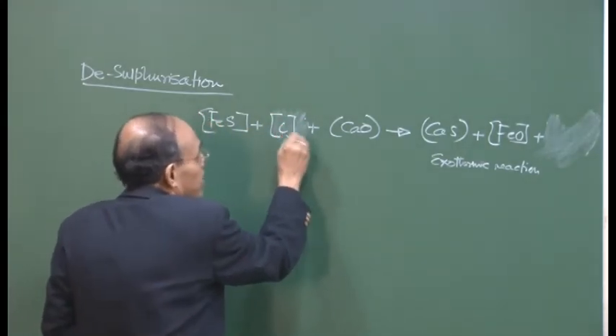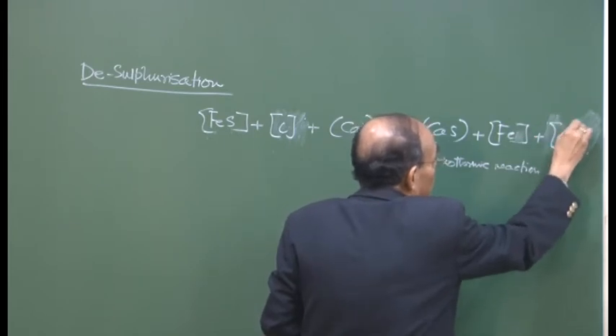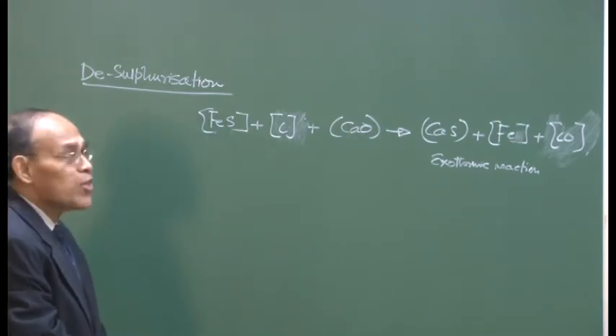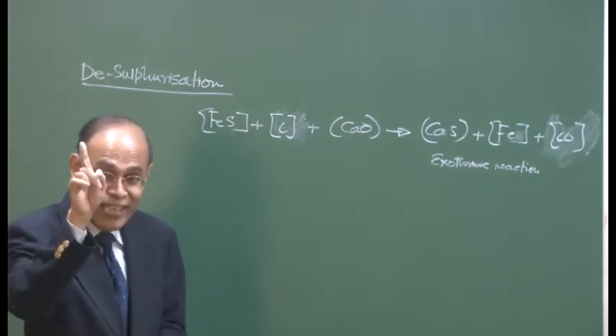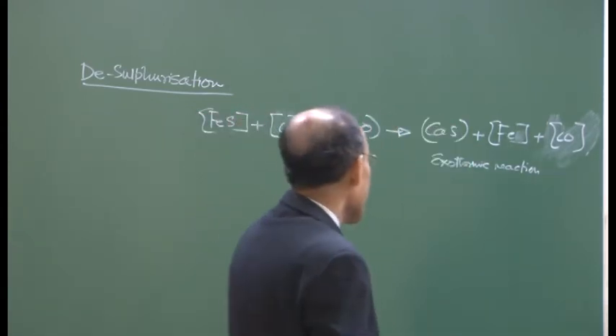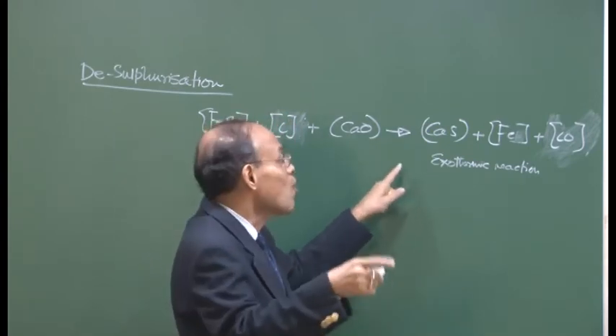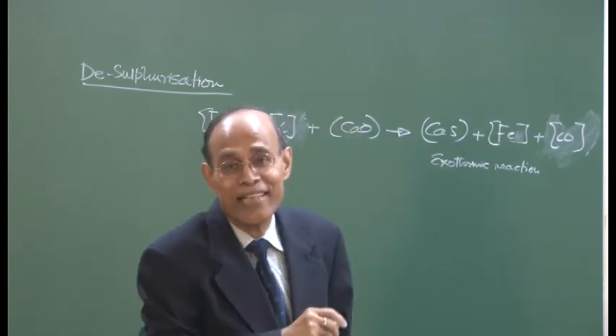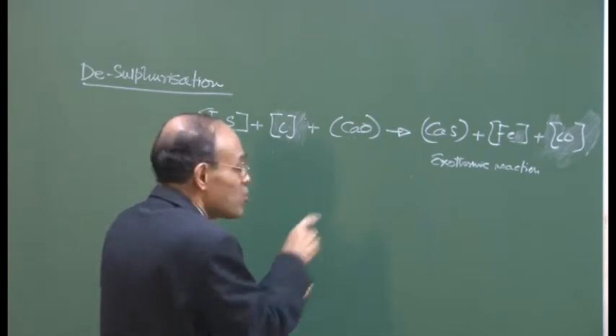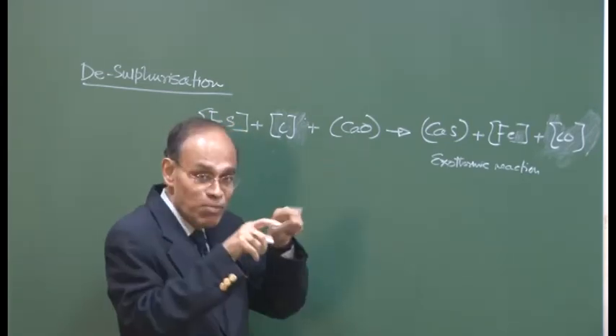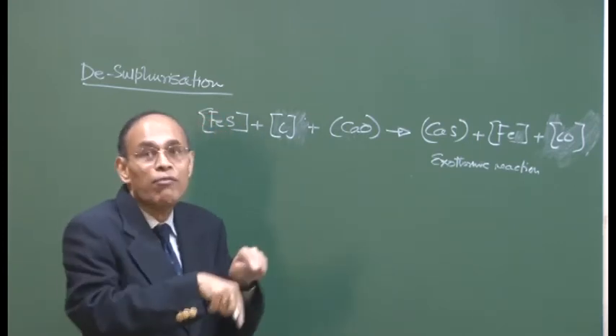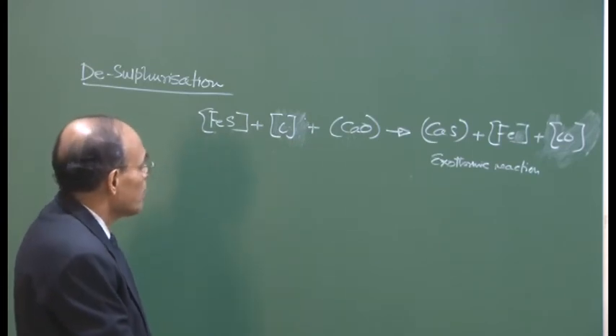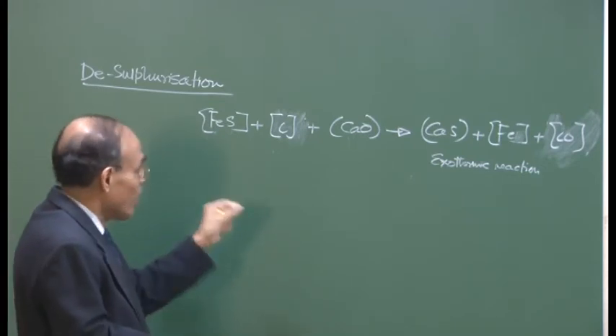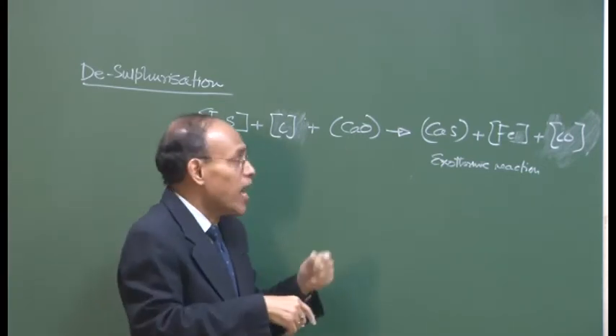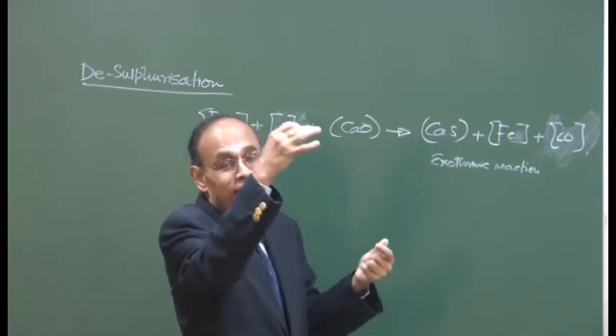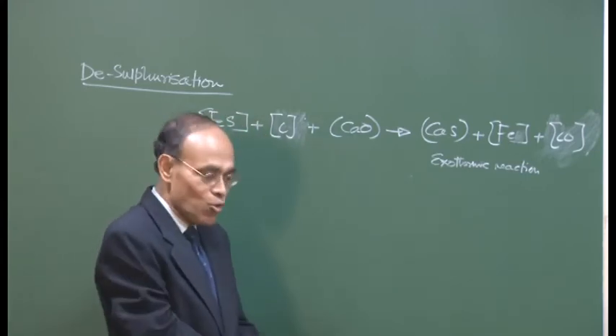But the moment I write it like this, there is exothermic heat generation because of carbon monoxide, and this becomes an exothermic reaction. So it is going to be facilitated at relatively low temperature, but I indicated explicitly when talking about blast furnace reactions in the hearth that we require a higher temperature. Higher temperature is seen to facilitate desulfurization, not for thermodynamic reasons but kinetic reasons, because the slag fluidity is an important part. This reaction takes place at the slag metal interface, so there is transport through the phases to the interface, particularly in the slag phase, which is a function of fluidity, and fluidity is a function of temperature. Higher fluidity happens at high temperature. Therefore, at high temperature this reaction is going to be facilitated.